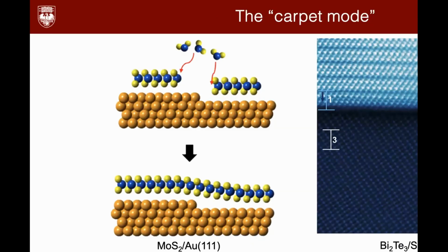So you might wonder, what have we done differently to achieve the supreme quality bismuth telluride films? I do not want to expand this into a materials science lecture, but I just want to mention one thing. Our film morphology is indeed quite different from what people traditionally thought about epitaxial growth of materials. In these films, if you look at the transmission electron microscopy data on the right, you can see that when there is a step edge on the substrate surface, the material does not really want to break.